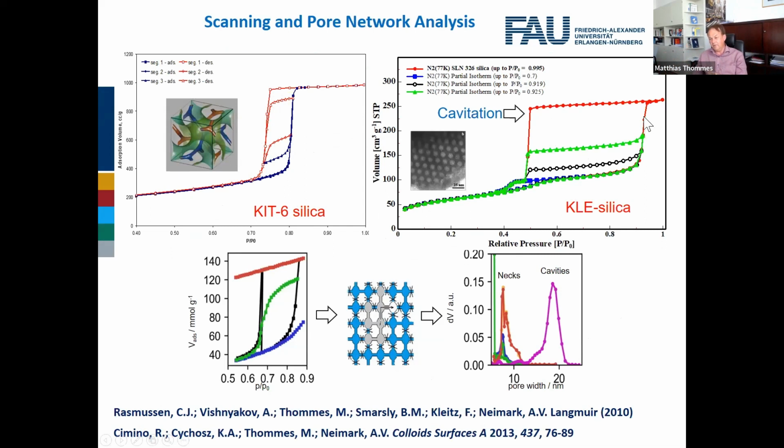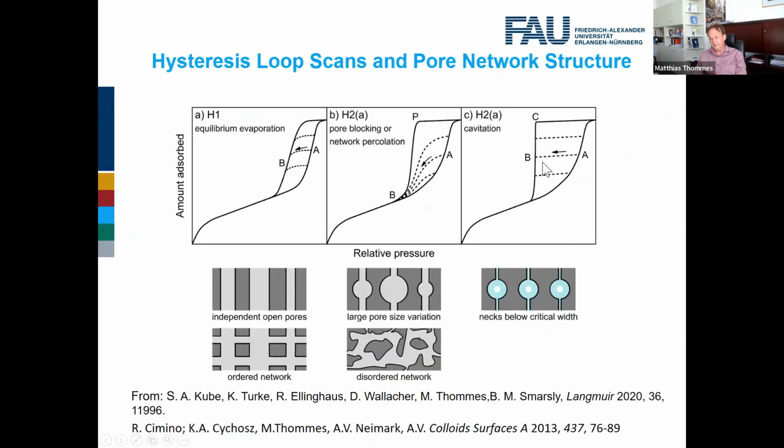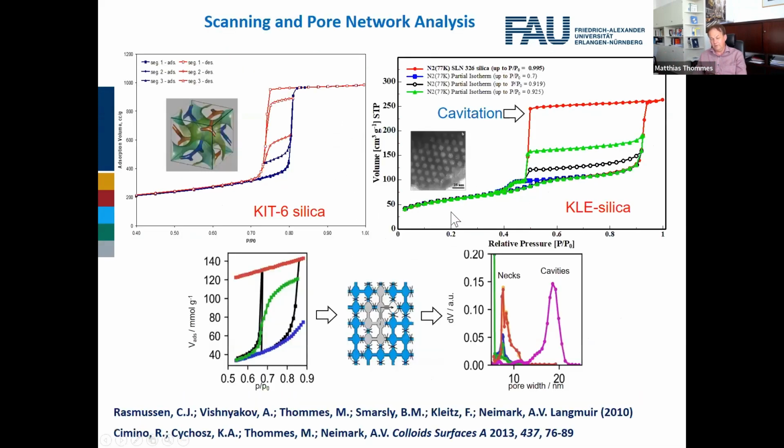Very large cavities of on the order of 30 nanometers. And you see here, we know that this is cavitation. And you see the scanning curves go right into this kind of desorption branch, as I have shown in the schematics. So this is the deal. This is what we want to do: essentially convert, finally, this information into pore network information and quantitative distribution of maximum cavities.